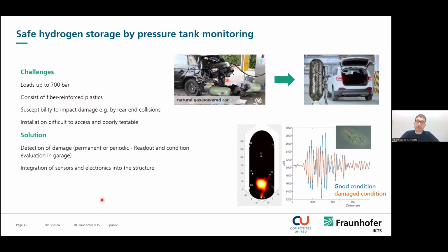Therefore, we have different methods, and on the example for the pressure vessel, for the automotive, we're talking now about type 4 pressure vessels with the loads up to 700 bar. Of course, they are made of carbon fiber reinforced plastics, but damage, impacts mainly, are not visible on the structure, but may cause failure of the structure. So one solution could be an installed sensor system that localizes damage.